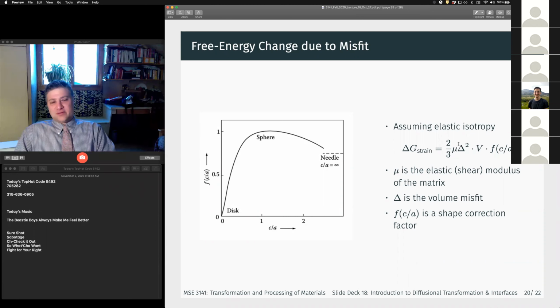We also have bulk modulus, shear modulus stuff. But in reality, that's not super important. It's just understanding that this is a strain energy per unit volume times the volume times a factor that corrects for the anisotropy in shape. And that gives us an estimate of the Gibbs free energy due to the coherency strains for a particle.